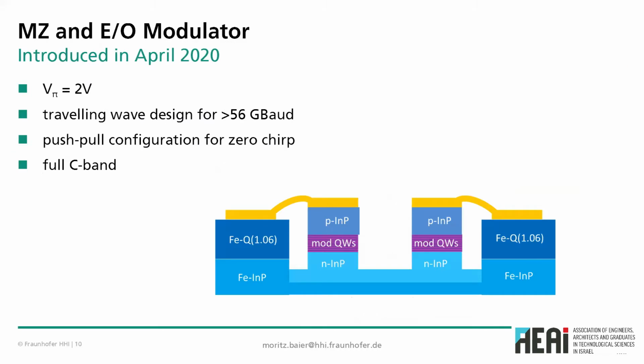But new in 2020, we actually introduced another building block to this end into our technology, which is a Mach-Zehnder modulator, which has 2 volts VPi and uses a traveling wave design to scale beyond 56 gigabaud. So here we are talking about frequency responses of around 60 gigahertz. It uses a push-pull configuration, which gives this extremely low VPi and also achieves an intrinsic zero chirp operation. And unlike the electro-absorption modulator, the Mach-Zehnder modulator operates across the entire C-band, not just at red wavelengths above 1560 nanometers.